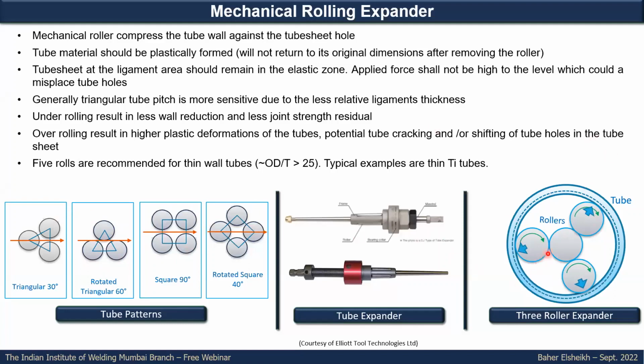This is an example of a roller with three rolls, and there are tools with 2 rolls, and in some tools 5 rolls, like what is usually recommended for thin tubes, like the examples of titanium tubes, where normally we can use 0.6 up to 0.8 or maximum 0.9 mm tube thickness. You have to apply 5 rolls in this case, otherwise you will face some cracking issues in the tube itself.